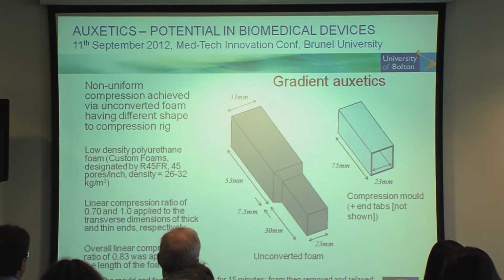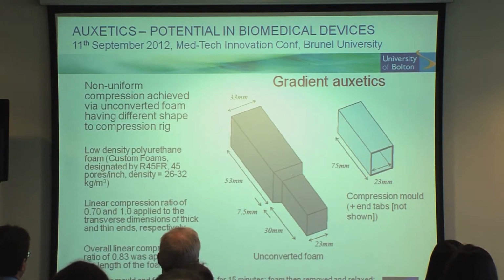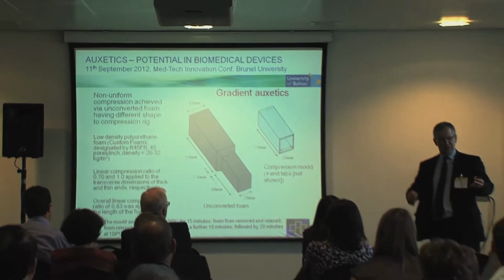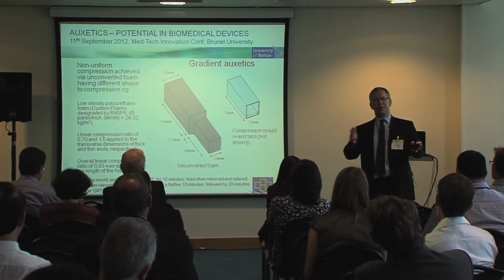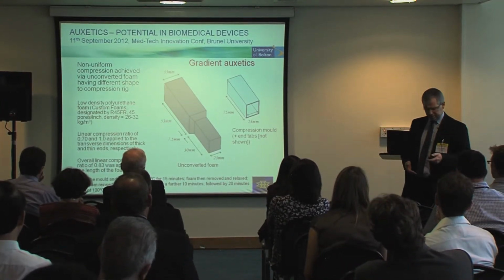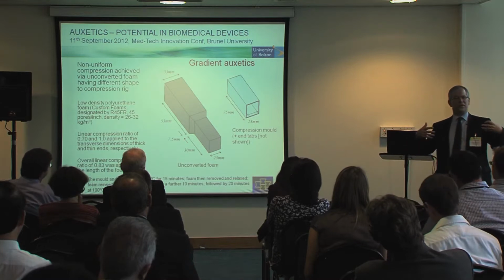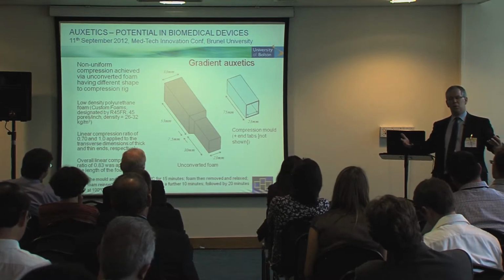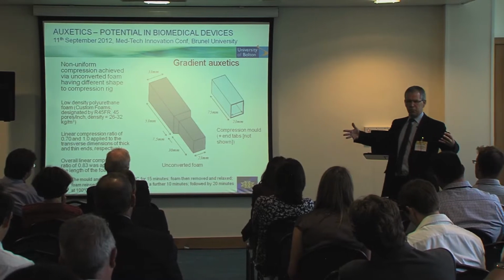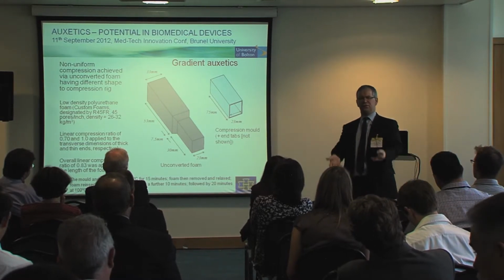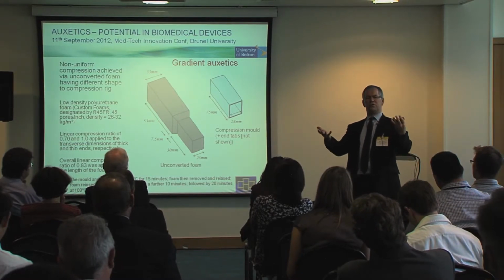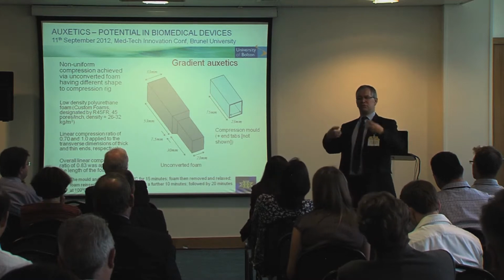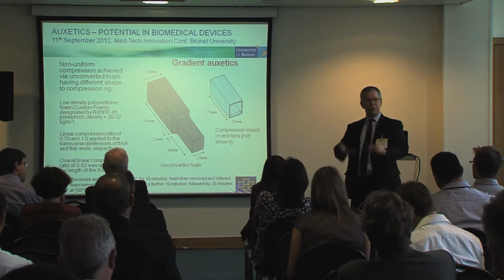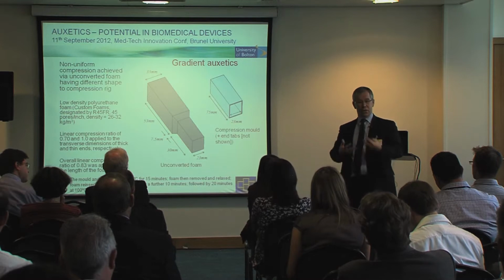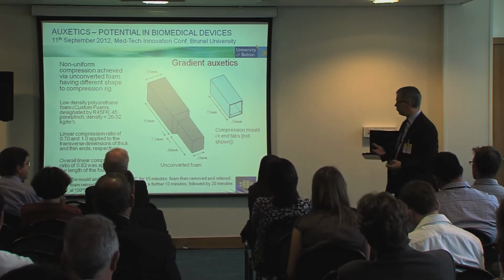Okay. Another thing that we've done recently is make auxetic materials where the properties and the structure vary in space, so gradient auxetics. The way you would make a normal auxetic foam, a thermoplastic foam, would be you'd start with a conventional foam, you put it into a smaller container, you heat it to its softening point. That allows the structure to relax into this new structure that will give you the auxetic effect, and then when you cool it below the softening point, it freezes the structure into that new structure. So that's how you would normally do it.